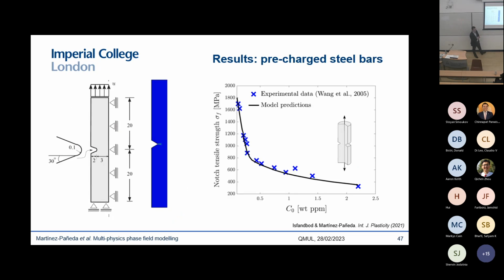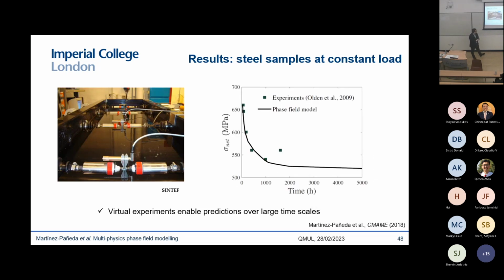And we can also get quantitative agreement with the experiment. So this is some pre-charged steel bars, and we're measuring the notch tensile strength versus the hydrogen concentration. And as you can see, the model seems to agree very well with the experiments. And this is another set of more interesting experiments. So these are notch samples that were immersed in a seawater bath. This was done in Norway, at Sintef. And then they loaded each sample at a constant load, but all of them at a different load. And what they were hoping is that one of the samples was subjected to a stress level that was small enough that you will not see any embrittlement. However, as you can see here, the symbols are experiments. They all fail relatively early for engineering purposes.